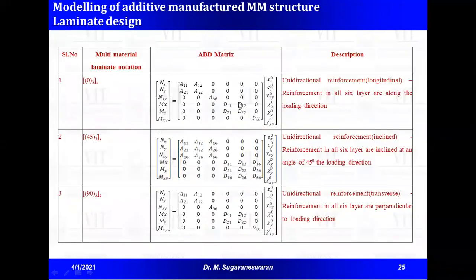Based on the CLT relationship, a few stacking sequences are considered. The first one is unidirectional. All three categories are unidirectional, but unidirectional in the longitudinal condition. So 3 represents 3 layers, and S represents symmetric of 3, so totally 6 layers. Above the axis it is 3, below the axis it is 3. And 45, where all the secondary material is placed with the primary material at 45-degree inclination. 90 is where the reinforcement is placed at 90 degrees in all 6 layers.